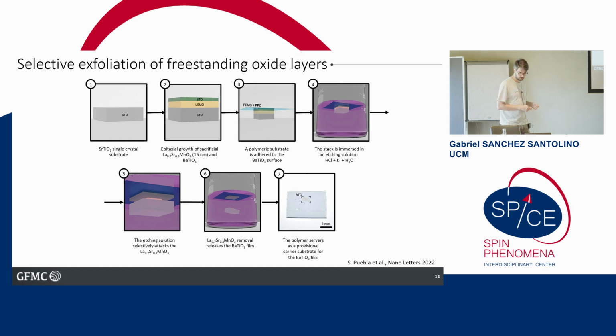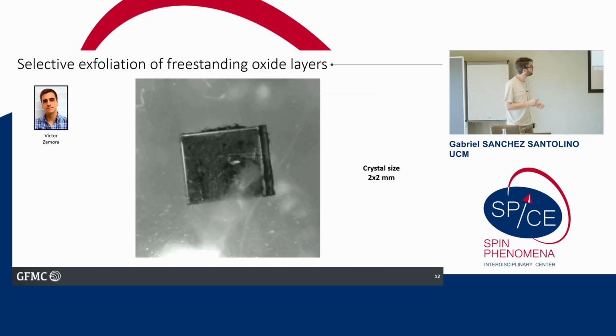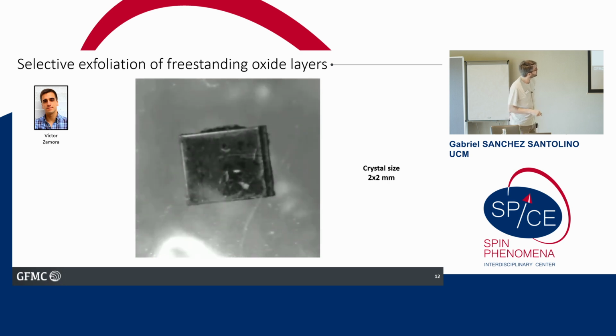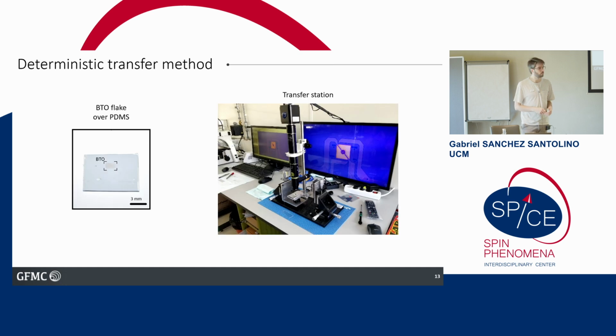And for those of you who work with 2D materials, now we can just do whatever we want with it, right? So I'm going to quickly show a video made by one of our students of this exfoliation process. You can start to see how the gray color starts coming from the edges of the crystal, and we are removing this manganate layer. After a few hours, this will be completely removed, and we have our freestanding ferroelectric layer. So we will have something like this. This is an optical image. You can see the layer a bit there, and then we can use conventional deterministic transfer to do whatever we want with it.